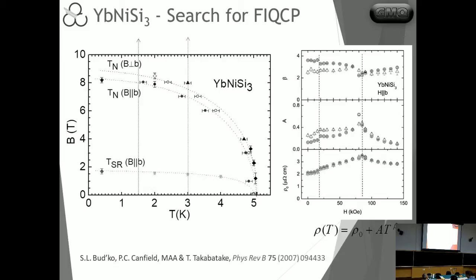So we did that later as a collaboration with the people from Ames Lab. And through that characterization, we could indeed come as close as possible to this region here at around 8 Tesla, which would represent a field-induced quantum critical point. But when we plot the resistivity parameters, right, the rho naught, the A, and the beta parameters here, we see that they don't really deviate that much from what is expected from a Fermi liquid. So it just seems that it's not there, at least coming from this one approach. We couldn't find it over there.